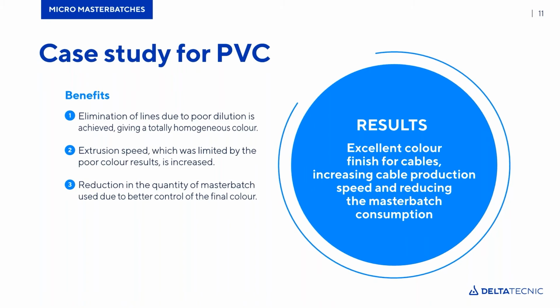In all three cases, going down with the size of the pellet, they reached control over the color, and they could also increase the speed. So it's not only a question of improving the quality of the outcome of the product, it is also a question of productivity and cost at the end of the day, because they could go back to higher speed production, and also they could reduce the dosage. So they could reduce the quantity of color master batches used, because the normal reaction of the technicians at the production line when they have problems with the color regularity is to increase the dosage. They go up with the dosage in an attempt to compensate with this lack of color homogeneity, but it doesn't work. What does work is going down with the size of the pellet.